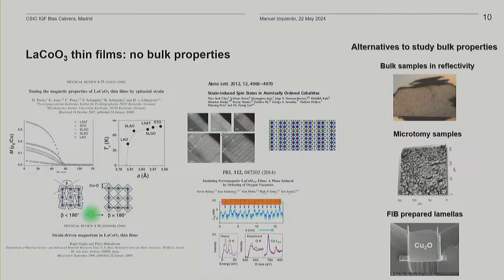You don't have this structure any longer; you have an orthorhombic one. So basically there was no way of doing this in the thin film, and we were left with 3 options. One is to study bulk reflectivity. Another is to do microcrystals using microtomy, and the third would be to prepare lamellas with FIB.